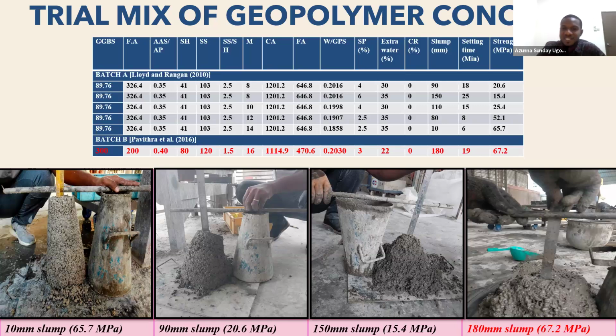So my emphasis is, from the recommendations, I think the maximum I saw in my literatures was 2. Most use 1, 1.2, 1.5, and then a maximum of 2, but even that is rare. You see, the 2 is rare. But for my case, there was even a situation where I used up to 6, but it didn't have much effect on the setting time.